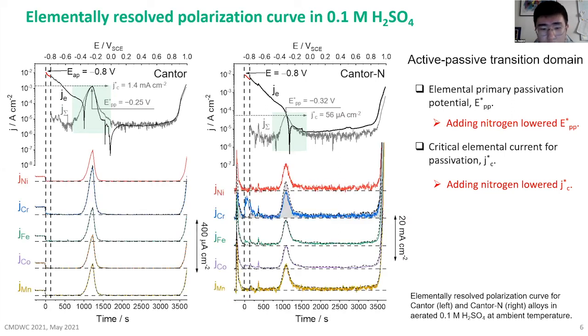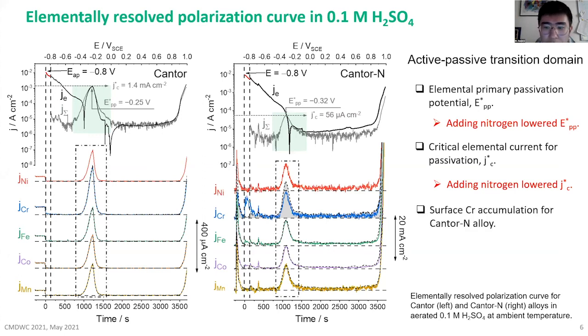And in the lower part of this curve, we showed the individual elemental current for both alloys, and also the congruent dissolution elemental current calculated and overlaid with the elemental current. We can see for the Cantor alloy in this active-passive transition domain, the elements showed congruent dissolution behavior. But for the Cantor N alloy, we observed the surface enrichment of chromium in this potential domain.